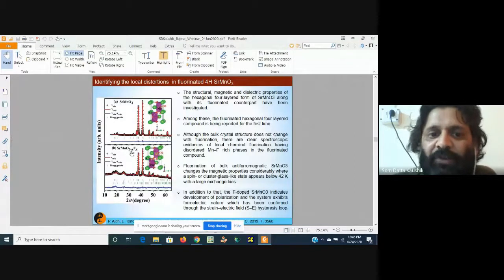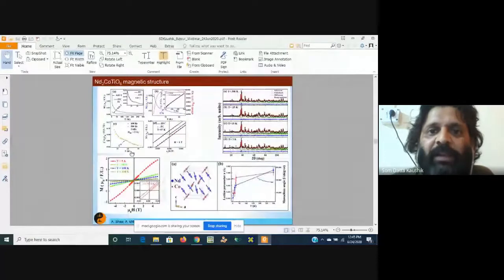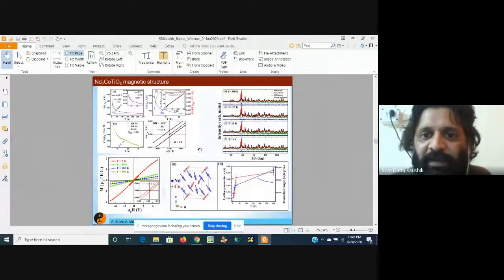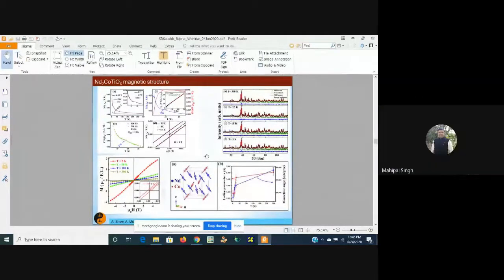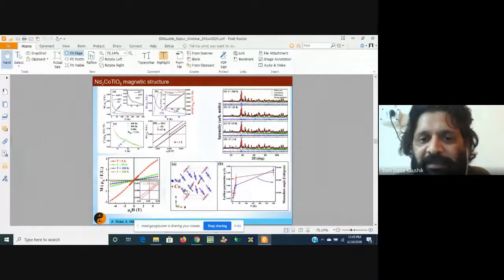Oxygen, being a low Z element, cannot be studied definitively by X-ray diffraction, but in neutron diffraction, as it is scattering length dependent, oxygen can be studied more conclusively. And one more example is a double perovskite, for which there was no report of the spin structure. We carried out neutron diffraction for this compound, and we can clearly see what the magnetic structure, which is antiferromagnetic, looks like.